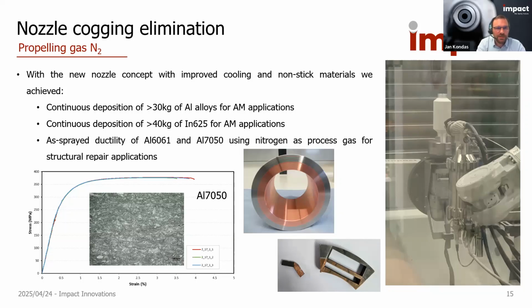So as you can see, we can deposit continuously more than 30 kilograms of aluminum alloys. This is our limit, what we tested so far, so it can be even more than 40 kilograms of Inconel 625 for AM application without any nozzle clogging. And also with this gun concept, we can deposit aluminum alloys in as-sprayed conditions with nitrogen process gas, reaching as-sprayed ductility for structural repair application.